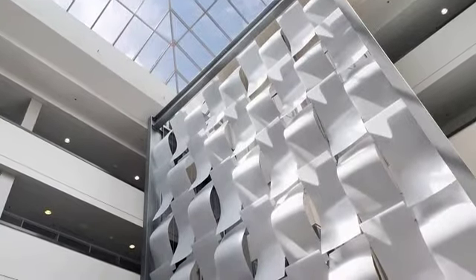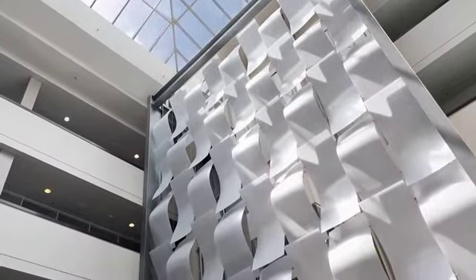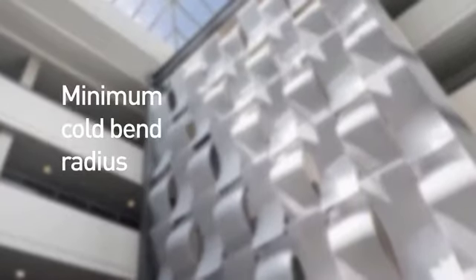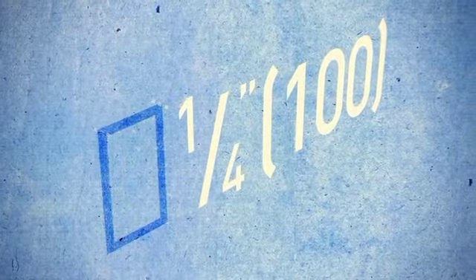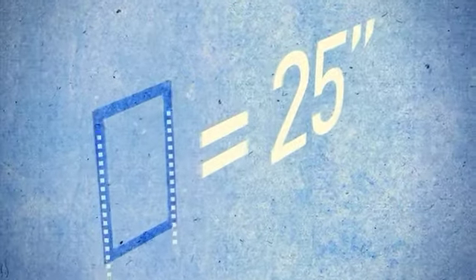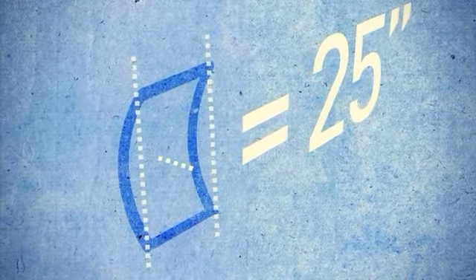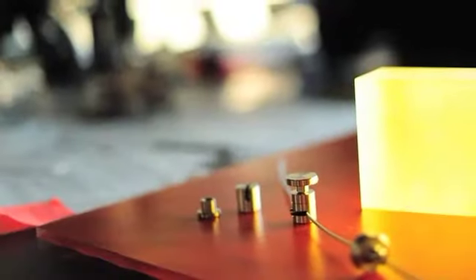One thing to consider when thinking about cold bending a material, though, would be first, the minimum cold bend radius. Generally speaking, the cold bend radius for any resin material, thermoplastic material, is about 100 times the thickness of the material. So for example, take a material that's 1/4 of an inch thick. Your minimum bend radius for that material would be about 25 inches. There are some complexities involved when considering cold bending, but material consultants and fabricators understand this very well and can help guide you in your designs.